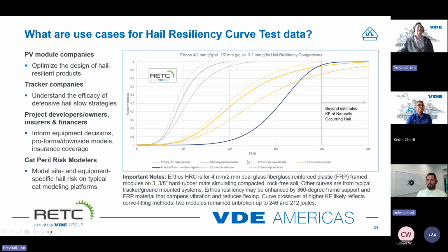Great. Excellent. And here's an example. Yeah, go ahead. Yeah, I was going to say one thing to get comfortable with for the whole team here is that it's okay in the glass testing world, under controlled environments, to just keep hitting it over and over and over again until the glass breaks. Especially with a blunt impact on surface one, you're not likely introducing flaws when it sees an ice ball and doesn't break. And you can then increase the energy, hit it in the same location, if you will, and you're not likely inducing flaws that would end up being rate limiting in that thing. And that's sort of something to get comfortable with.